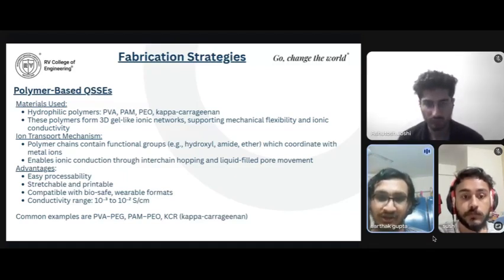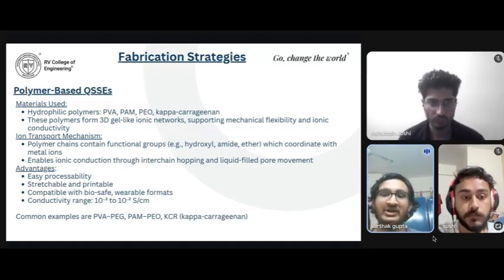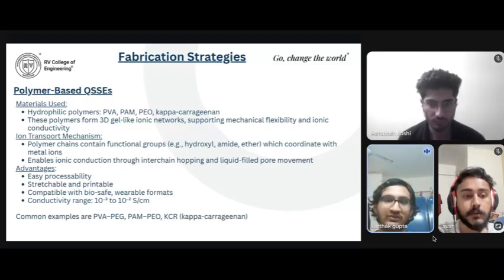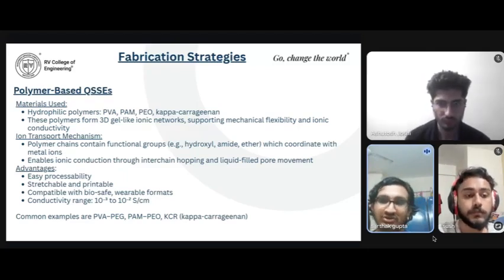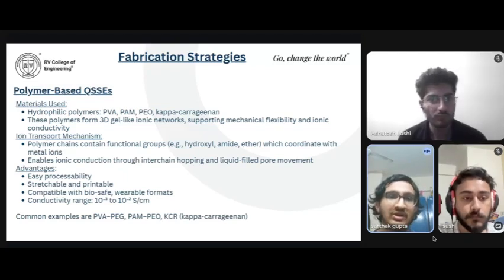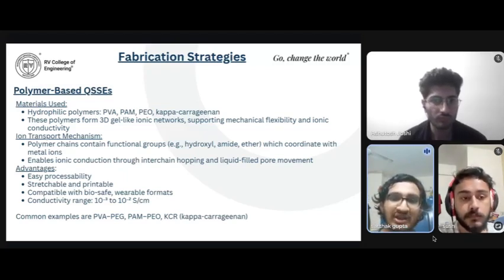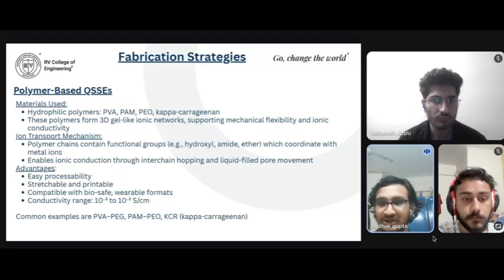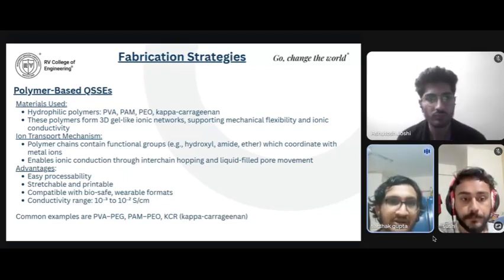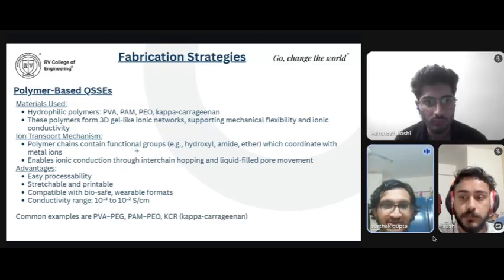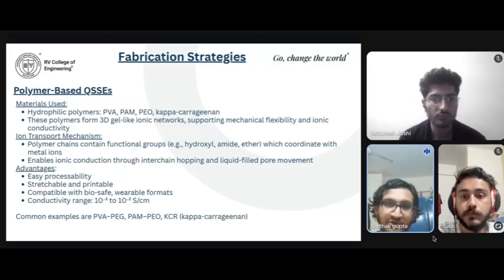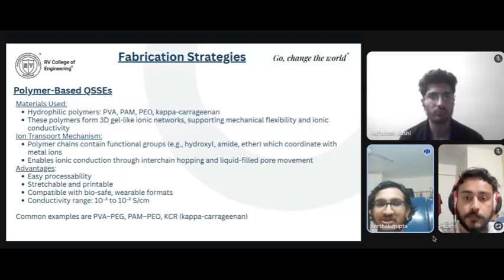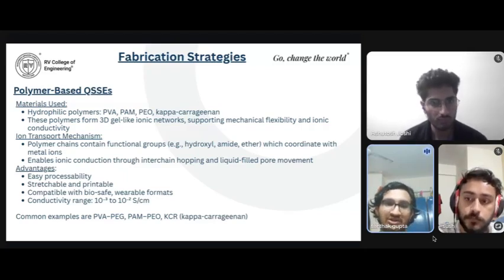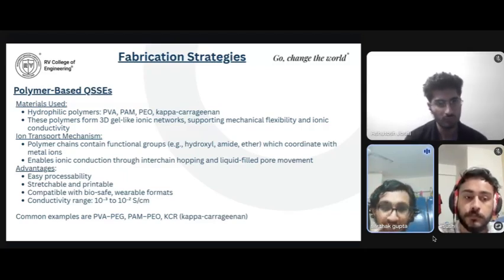electrolyte, which is soft, stretchable, and provides a conductivity in the range of 10^-3 to 10^-2 Siemens per centimeter. It is highly compatible with low-cost fabrics and wearable integration, like in watches. As for the ion transport mechanism, as I mentioned, the polymer chains use functional groups like hydroxyl and amide, which coordinate with metal ions like Zn2+. All these things make polymer-based fabrication a very fundamental and effective strategy.